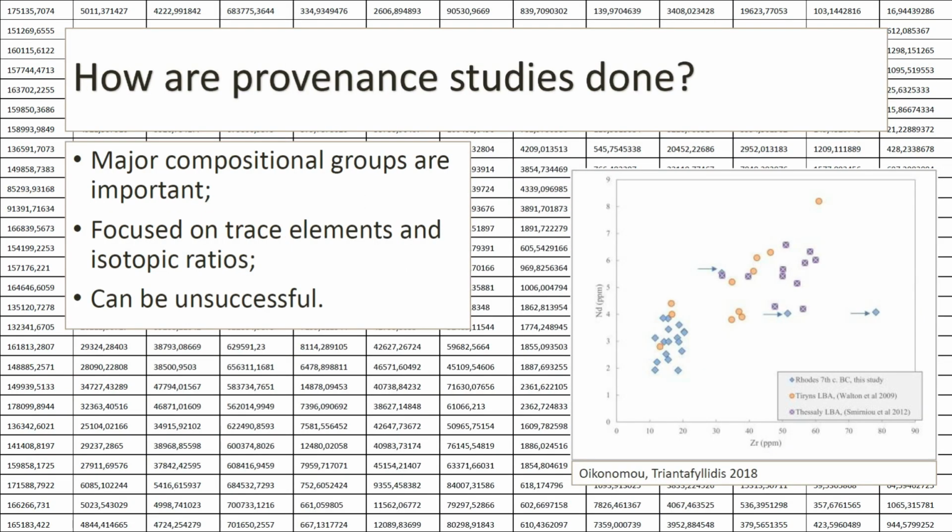Provenance studies are extremely fascinating. Basic paths of those are discrimination and grouping of objects. They can be done by finding similar objects by composition and structure of known origin and by comparing the objects chemically to its raw materials. This can be done on different levels. Studies that give the most of certainty are the ones based on trace elements content and those based on isotopic ratios. Even with the most advanced technologies, the success is not guaranteed.